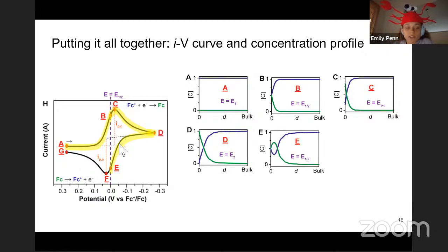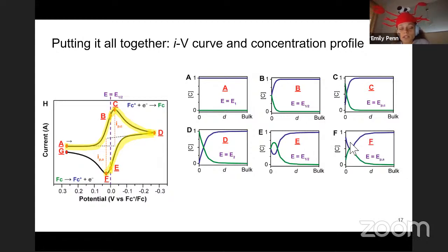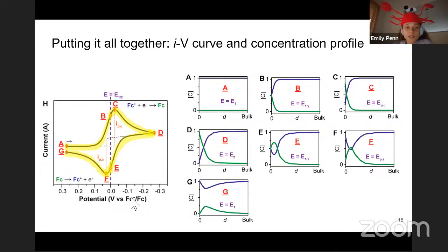Then after we reverse the potential and we scan to E, we're in a similar case as we were at B. So we again have an equal concentration of the oxidized and reduced species at the electrode surface, but our bulk concentration is still that the oxidized species is at a concentration of 1. So that's why we have a different shape than we do in B. But then as we continue, we see the same thing that we saw on the forward scan, where now we're depleting the concentration of this reactant species. And then as we get back to the starting potential, our concentration profile looks similar to how it looked at A.